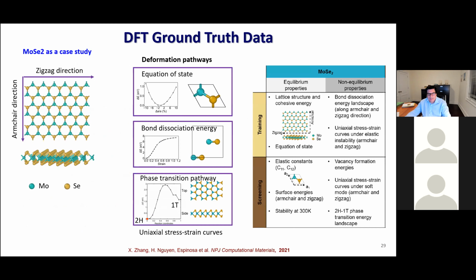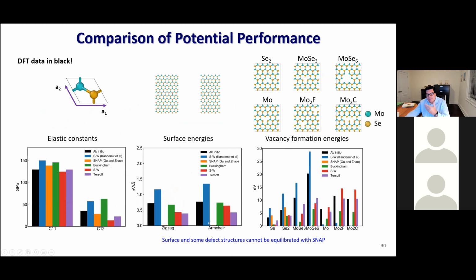So let me show you briefly some of the results. Again, DFT data is your ground truth. You run for all these types of properties. Here is a summary again, and I will start showing you the behavior of the different potentials. DFT data is in black through all these comparisons. If you look at the elastic constants, the two potentials that we saw that were parameterized near small deformation do very well, because these are elastic constants, but they do extremely poorly when you look at surface energy, for instance. Like SNAP, one of the machine learning potentials, doesn't converge for surface energies.